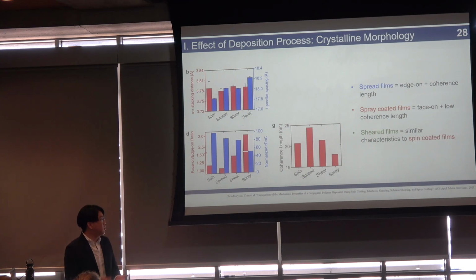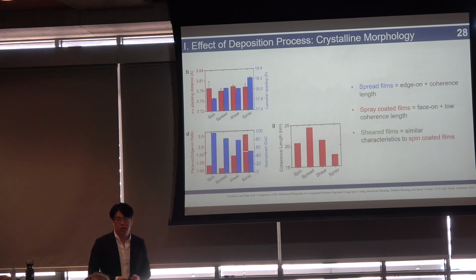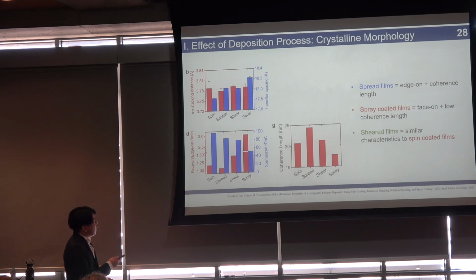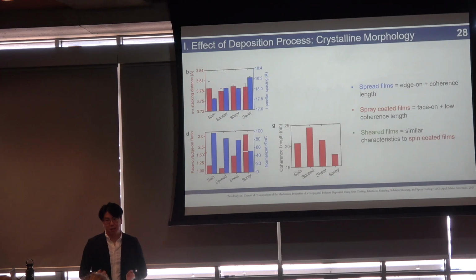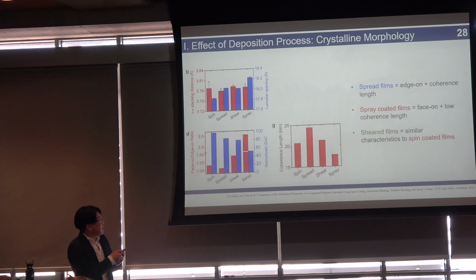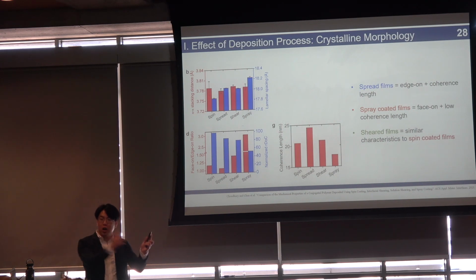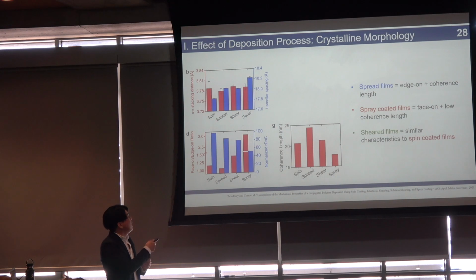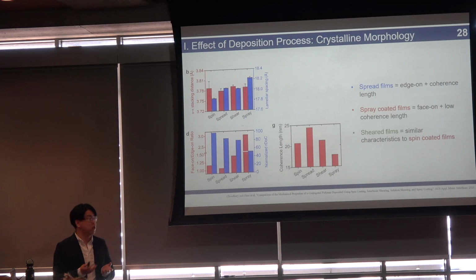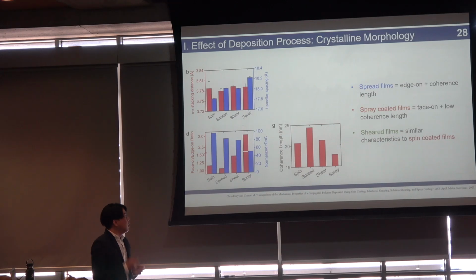They have a very high face-on texture, and they have a very low coherence length. And sheared films have pretty similar characteristics to spin-coated films. So we know that because of the edge-on texture of these films, we should expect charge transport to be better across the film than vertically. Whereas for face-on films, the opposite is true. Charge transport should be favored in the vertical direction.